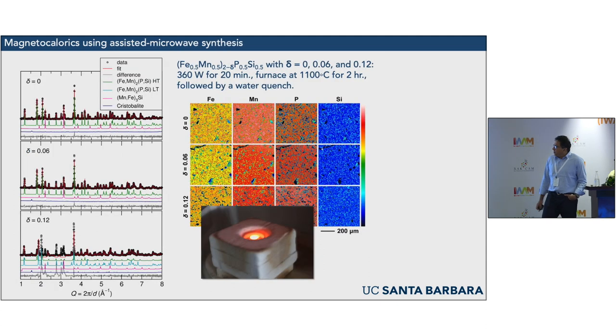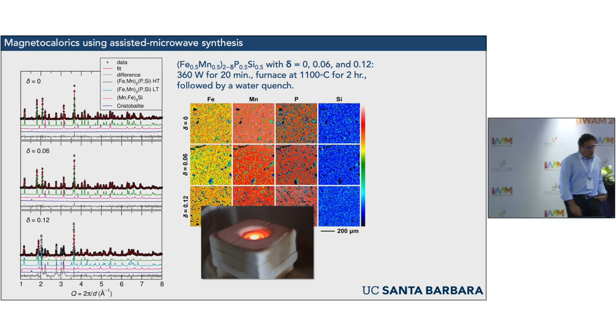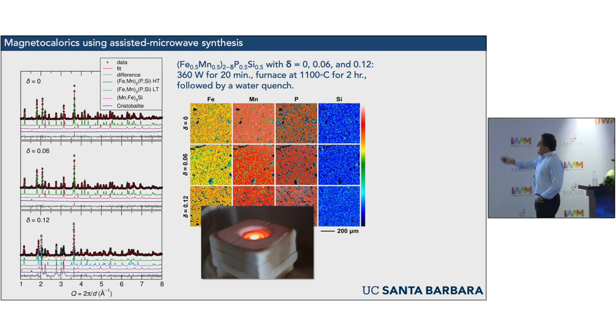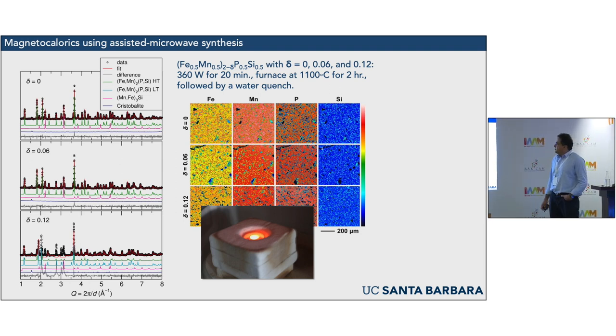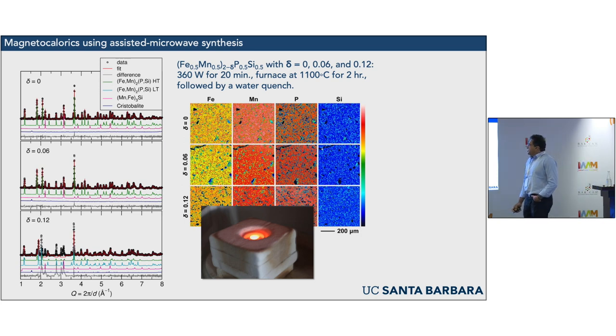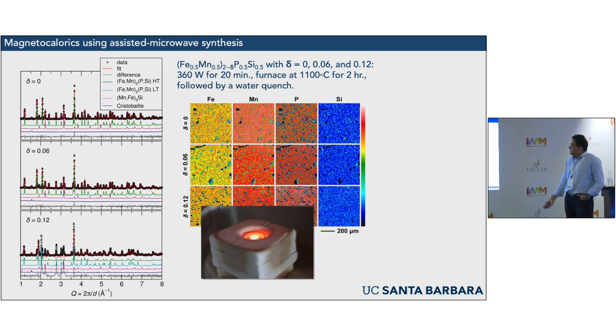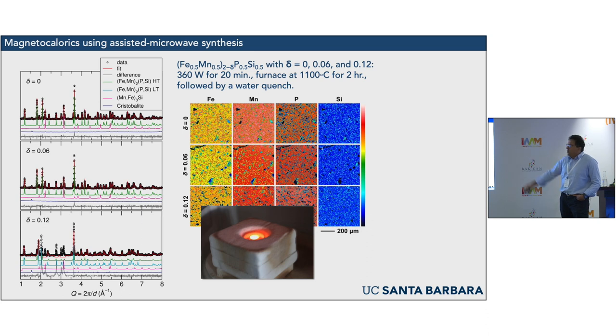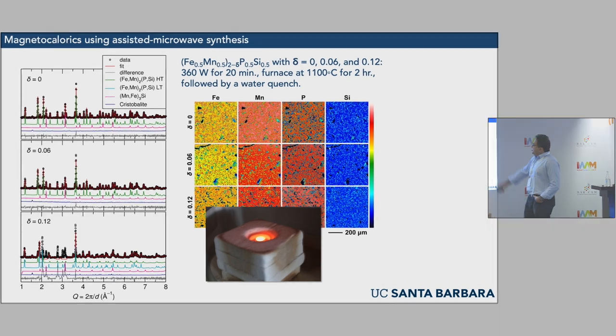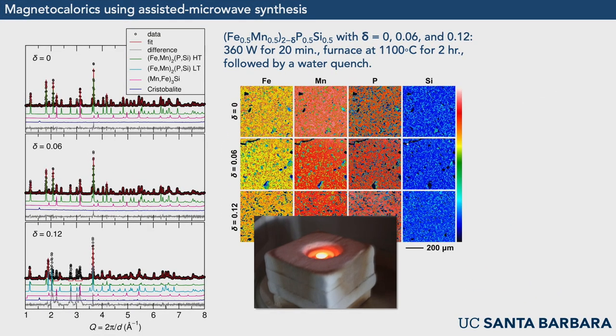The first challenge from BASF was to make these iron-manganese-phosphorus-silicon materials more rapidly than the original synthesis, which required extensive cycles of grinding and annealing. In our lab, we like to use domestic microwave ovens to do rapid reactions at high temperatures. We found we can make the materials phase-pure in about 20 minutes in the microwave oven, followed by a quick anneal. After 20 minutes in the microwave, we already get the pure sample, though the annealing is important to fully develop the magnetic properties.